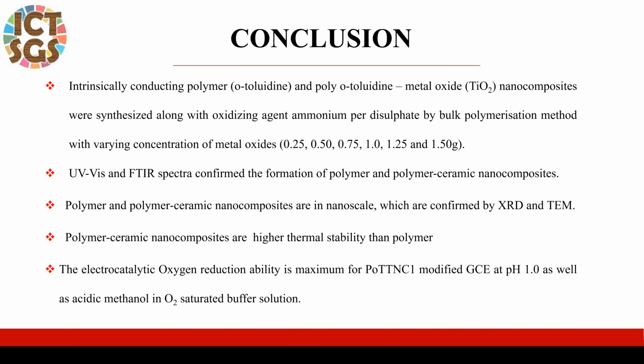Conclusion. Intrinsically conducting polymer and polymer metal oxide nanocomposites were synthesized along with the oxidizing agent ammonium persulfate by the bulk polymerization method with varying concentrations of metal oxides. UV visible and FTIR spectra confirm the formation of polymer and polymer ceramic nanocomposites. Polymer and polymer ceramic nanocomposites are in nanoscale, which is confirmed by XRD and TEM. Polymer ceramic nanocomposites have higher thermal stability than the polymer.